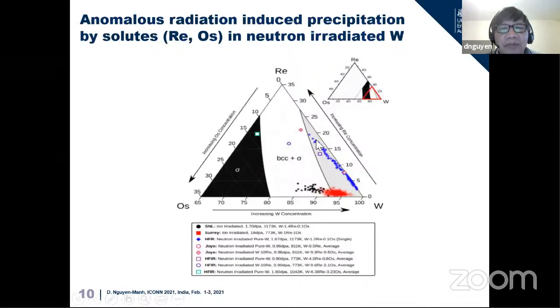The summary of the experimental observation is that the samples we look at are in the ternary phase diagram of tungsten, osmium, rhenium, essentially in the BCC solid solution limit of tungsten, and the radiation induced precipitation is only happening in this region. That's why we call it anomalous: in a normal ternary alloy you have the BCC phase, but even under irradiation you see precipitates or a second phase forming in the BCC region. We call it anomalous because it's inside the BCC region and it's not the sigma phase or an intermetallic phase in the alloy.